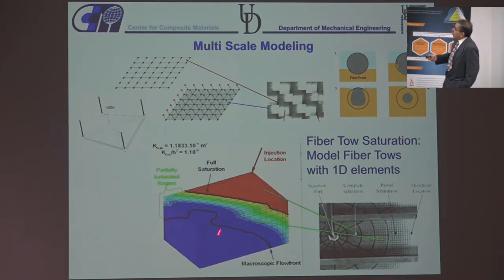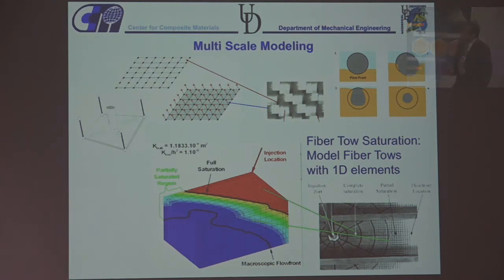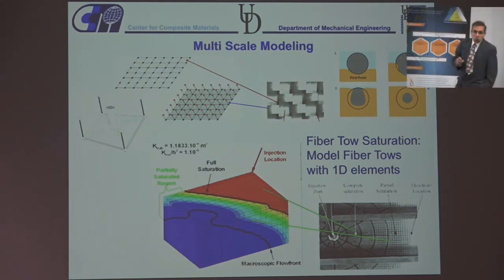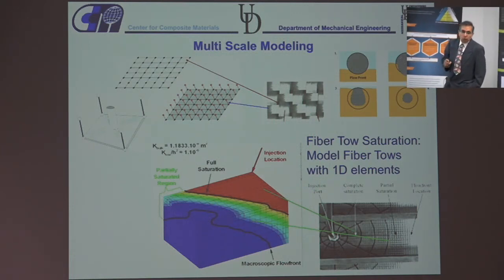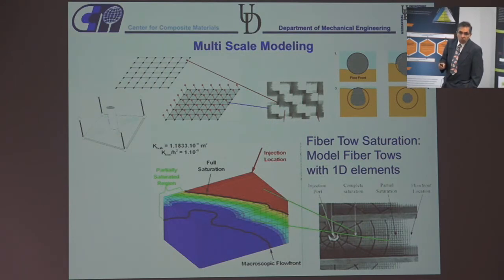Okay, so what is the advantage of doing it this way in a manufacturing practice? What I want to do is keep injecting the resin not when this line arrives at the vent, but until this line arrives at the vent, because that will ensure that my toes are also filled. So what I would do is let the resin bleed, just let the resin go to waste a little bit till this line arrives here. So the simulation can tell you how long you have to wait before you shut off your injection.